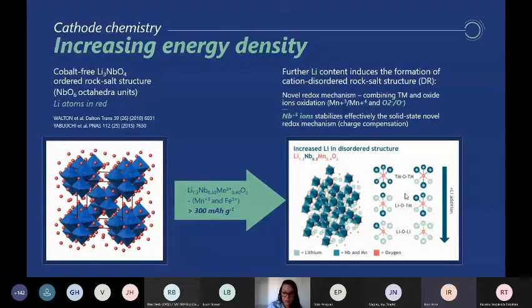And then in a solid state reaction, we can see a charge compensation reaction because of the lithium excess in the structure. To balance this charge compensation reaction, you need a high valence metal, in this case, niobium. In this study, niobium increased the energy capacity of this material, almost double the theoretical capacity compared to using only manganese metal, manganese oxide.